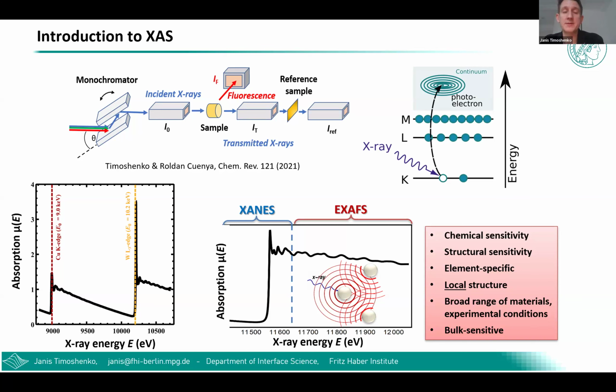But another important advantage of XAS is that you can do these experiments quite easily under operando conditions. You can measure your catalyst under actual working conditions, in the presence of electrolytes and applied potential. So you can really see on the fly how the catalyst is responding to changes in your electrochemical protocols and what happens with its structure, especially if you have some idea about what possible structural motifs you could encounter.